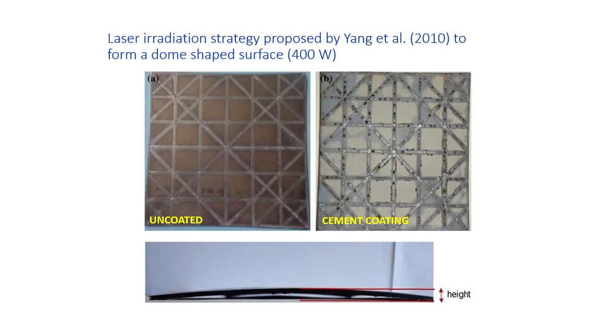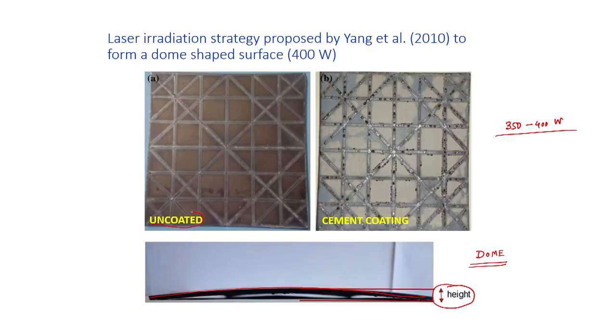Here you notice that a dome shape pattern was generated when we applied around 350 watt to 400 watt of laser power. Then a certain height was obtained and that shape was something like a dome. So, a dome-shaped workpart was developed. It was tried with uncoated material, an uncoated sheet, and it was also tried with a cement coated worksheet. For the cement coated worksheet, of course, the dome height was considerably larger than for the uncoated sheet.